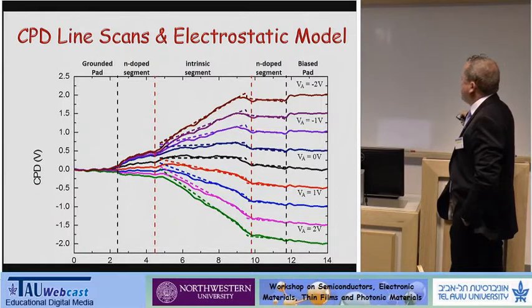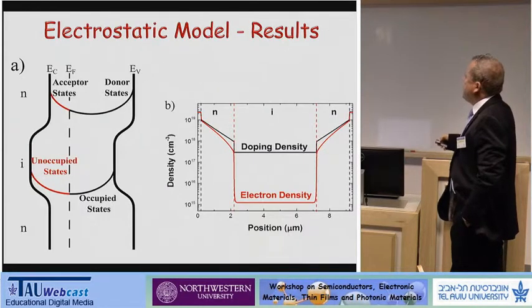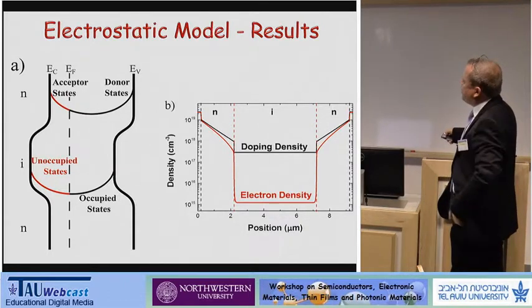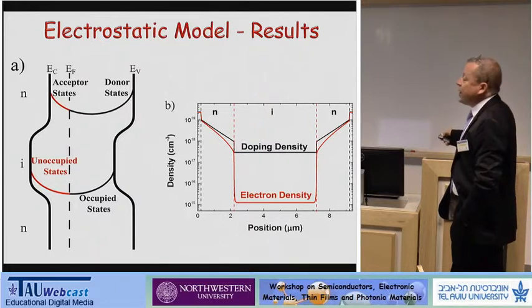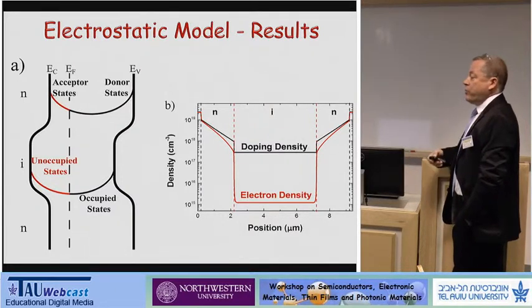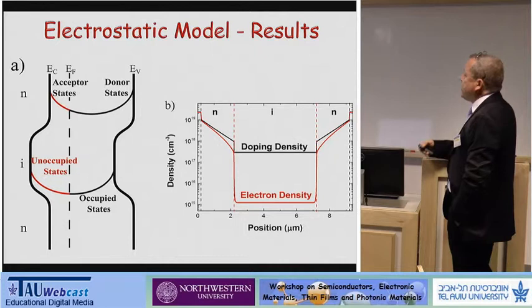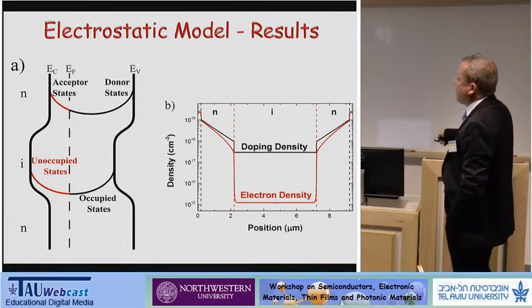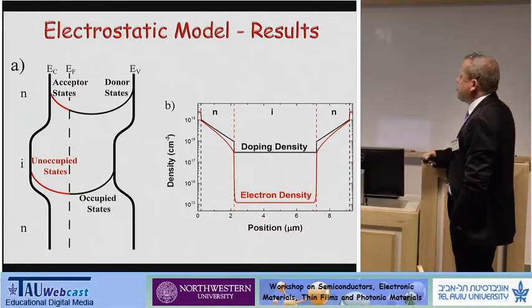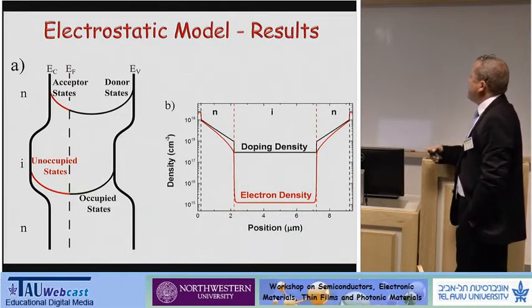Actually, this applies different biases on the nanowire devices. The end results: this is in a 90 degrees rotation, the band gap of the polysilicon nanowires. We were able to get the interface state concentration and distribution at the grain boundaries, assuming there are no such states inside the grains. So you see we have a well-behaved result, consistent with what is reported in the literature for polysilicon nanowires.